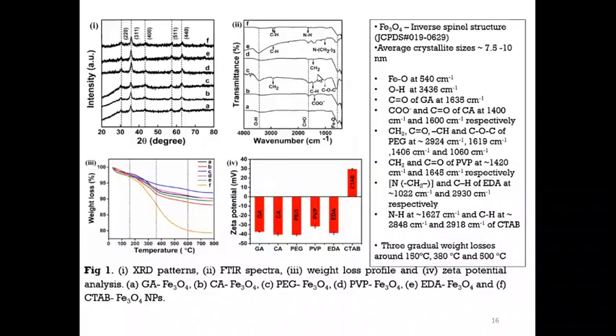Fine. So this confirms the functionalizations, and the X-ray pattern confirms the formation of the iron oxides. For more confirmation of the formation of the iron oxide, the presence of Fe2+ and Fe3+ ions can also be confirmed through XPS, X-ray photoelectron spectroscopy.